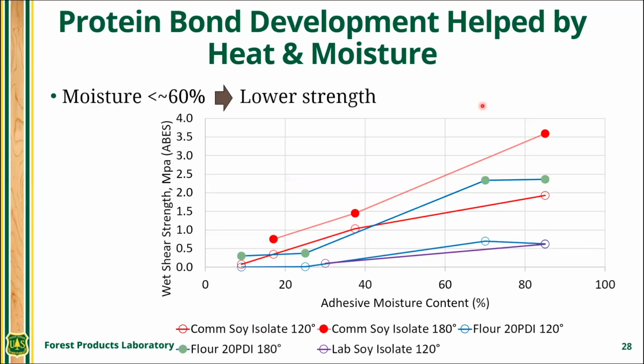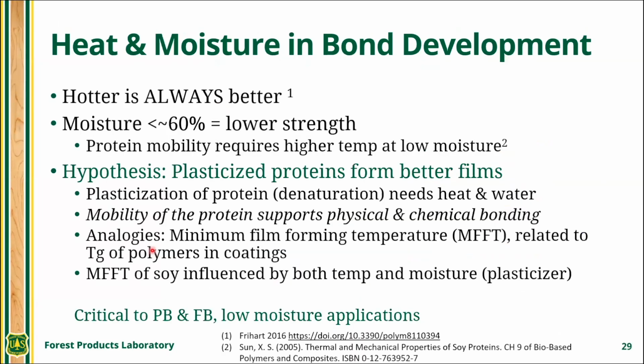Similarly, the moisture content of the adhesive also has a role. So this is the moisture content of the adhesive applied to an ABES, and then they were pressed, some of these at 120 and some at 180. But here's a particular soy protein at 85% water, 37% water, 18% water. When it's applied to the ABES and then immediately pressed, you can see that the water helped. When it went on wet, we got 3.5 megapascals. When it went on dry, we got less than 1 megapascal. So the water helps to form the bond. These are all tested wet. So hotter is better.